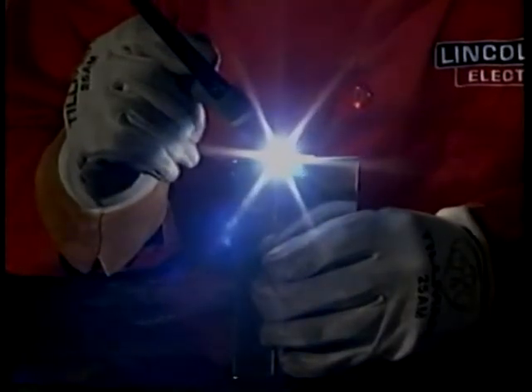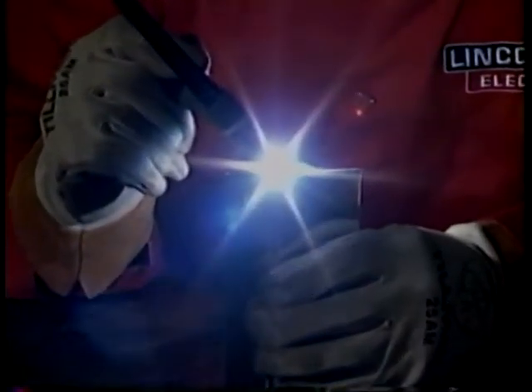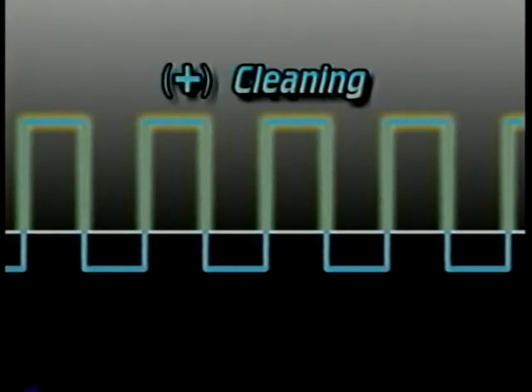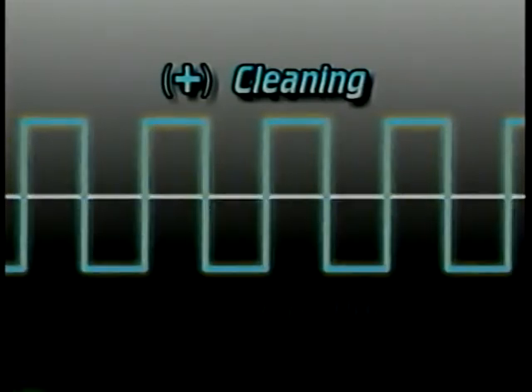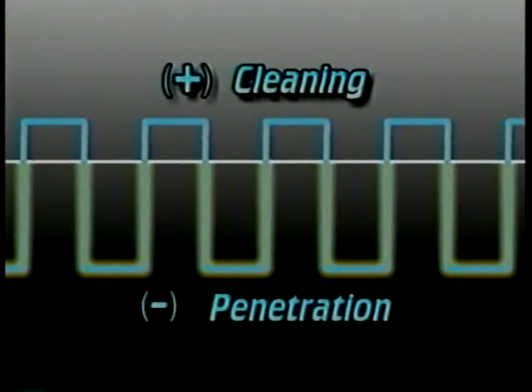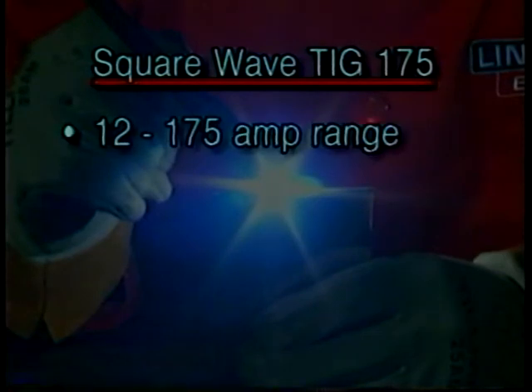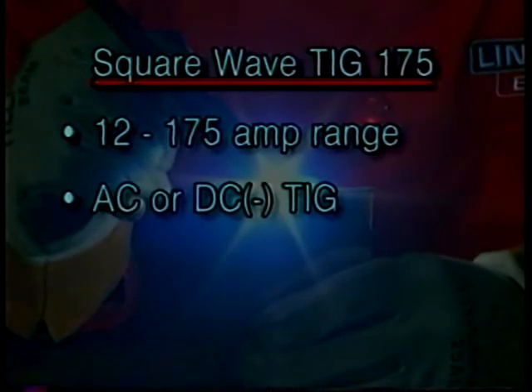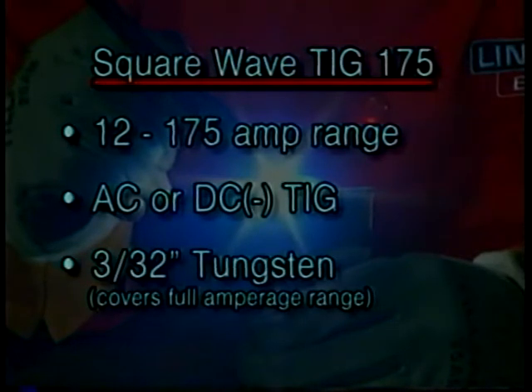The AC TIG welding of aluminum with your Square Wave TIG 175 offers a number of advantages. With the square wave design, the positive portion of the AC wave causes heating of the electrode and cleaning action. The cleaning action removes the heavy oxide coatings on aluminum. The negative portion of the AC wave minimizes electrode heating, so there's no melting and more heat is concentrated on the work. All this allows you to weld through the complete 12 to 175 amp range in AC TIG or DC negative TIG, needing only a 3/32 inch 2% thoriated tungsten electrode.